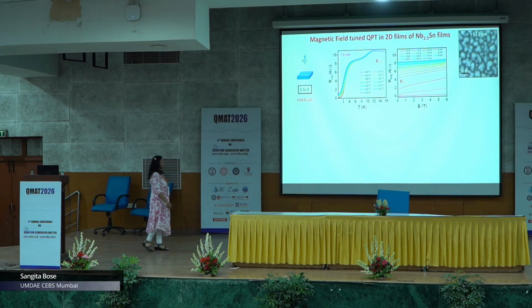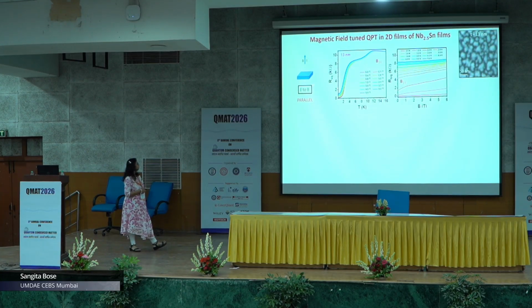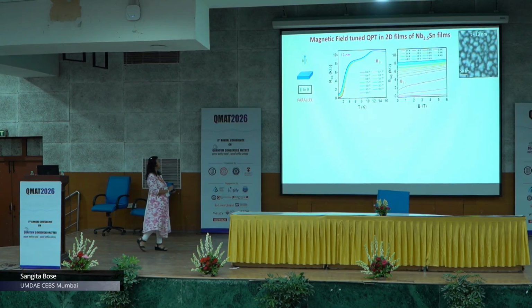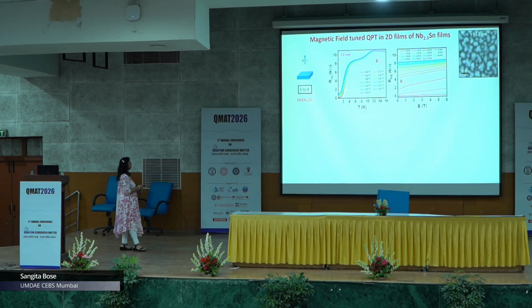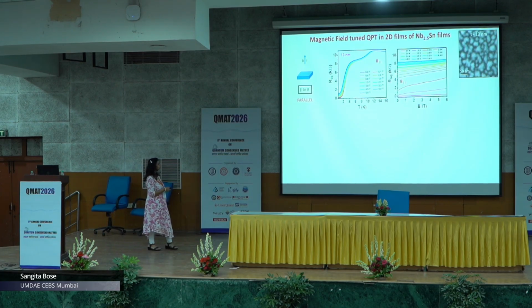Now we want to look at the magnetic field tuned quantum phase transition. We first take this 13 nanometer film and try to measure the temperature dependence of the resistance as a function of different magnetic fields in the parallel orientation. Of course, there is nothing much happening. As you increase the magnetic field, you just start getting this pair breaking effect. So you have some effect over here. If you look at the magnetoresistance isotherms over here, you do not see much.